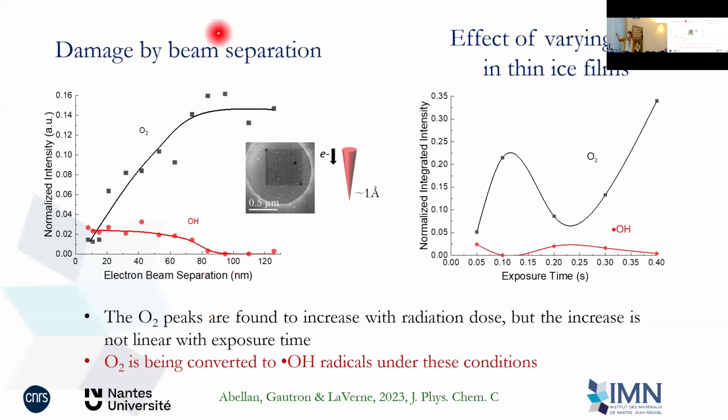But, yeah, you see that there is some diffusion, some kind of effect where these things see each other in the core loss. We are not in the low loss, so this means that it's a real thing of things diffusing away and interacting with something that is happening nearby. And you have to go really far away, like 70 nanometers, for this thing to not happen.